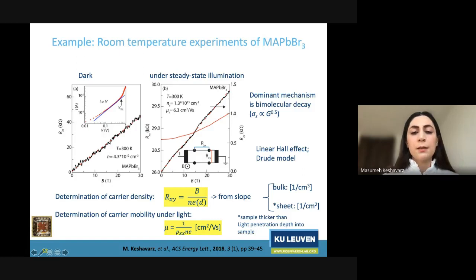We measure the Rxx, you see on the left axis, and on the right axis is Rxy. The Rxx is the magnetoresistance in the presence of the magnetic field, and it shows the classical orbital effect, the quadratic dependence, and the Rxy is linear. We extracted the carrier concentration, which is one order of magnitude higher than in the dark under illumination. I must say that for the dark measurements, we extracted the carrier concentration for the bulk sample, but under illumination, because the penetration depth of the light is only 80 nanometers, we consider it as a sheet conductivity.